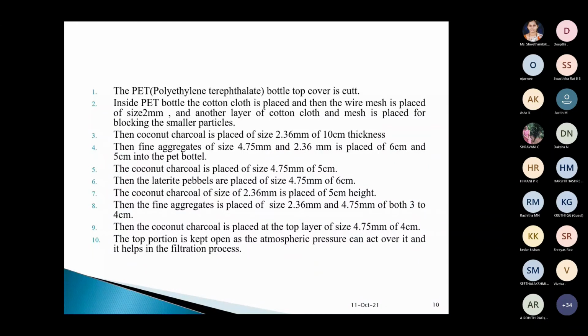Then coconut charcoal is placed, of size 2.36 mm to 10 centimeter thickness. Then fine aggregate of a lesser size. Then again coconut charcoal of a somewhat larger size. Then laterite pebble. Then coconut charcoal of some more larger size. Then fine aggregate of more size. Then the coconut charcoal top layer of size 4.75 to 4 centimeter. The top portion is kept open. Why? Because atmospheric pressure can act over it and it helps in the filtration process.